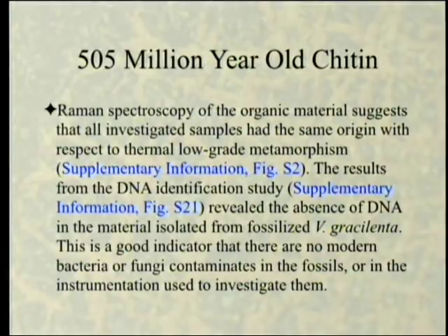Raman spectroscopy of the organic material suggests that all investigated samples had the same origin with respect to thermal low-grade metamorphism. The results from the DNA identification study revealed the absence of DNA in the material isolated from the fossil Vauxia gracilenta. This is a good indicator that there are no modern bacteria or fungi contaminants in the fossils or in the instrumentation used to identify them. At least if there is any contamination, it's of dead body parts, not living organisms, because the living organisms would have some DNA still left in them.